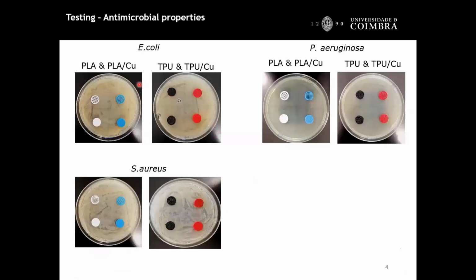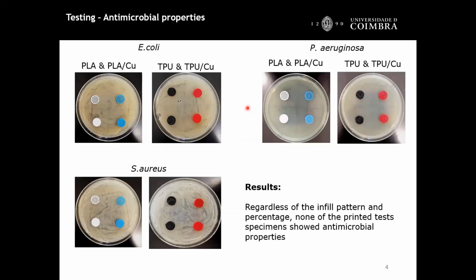The fact is, when you process it, and we processed it with several infills, geometries, and densities, and we tried with Escherichia coli, Staphylococcus aureus, and Pseudomonas aeruginosa because they are in the top 10 of the most dangerous infectious bacteria, none of them presented any antimicrobial property. So the problem is that what is advertised for commercial filaments may not be true once you have printed your specimens, okay?